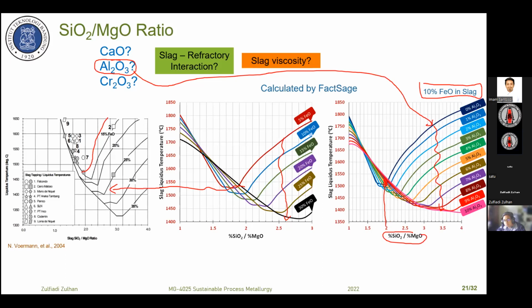So we can reduce the melting point a little bit, but at high silica to magnesia ratio, the melting point decreases by more than 100 Celsius degrees. It's very high for sure. Maybe this decrease of liquid temperature is the cause of the slag being very aggressive to the refractory material. Besides, the silica content is high, and silica is an acid oxide that can react with MgO, a basic oxide. MgO we use as refractory material. In the other case, by the presence of alumina, the melting point will also decrease. So later on, we should measure the slag viscosity. This is based on calculation.